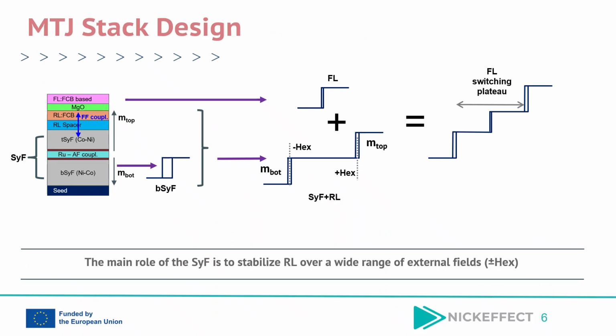The MTJ stack design starts with the development of the bottom multilayer system, bSyF, with strong perpendicular magnetic anisotropy, which is subsequently used for the formation of the complete SyF structure. A suitable seed layer is required to ensure the proper growth, texture and crystalline quality of the cobalt-nickel multilayer system.